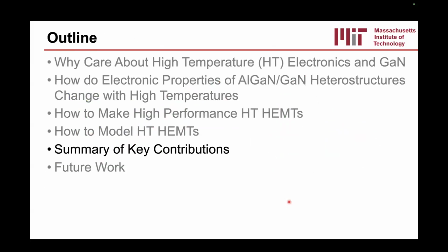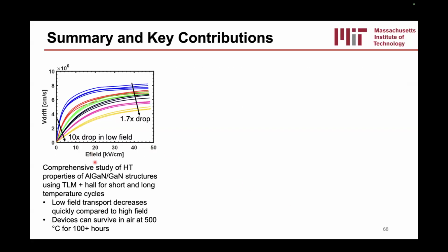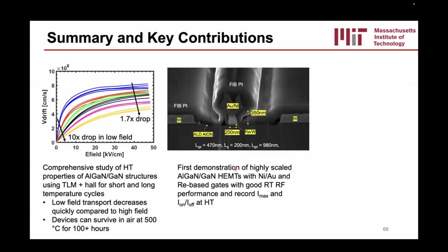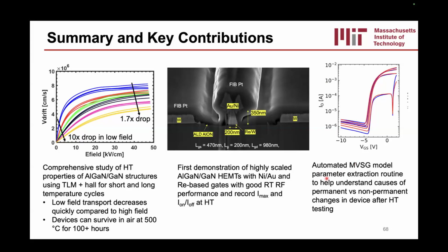Great. So I'll end now with a summary of some of the key contributions of this thesis. All right, so we've learned a good amount about the high temperature properties of GaN HEMT structures. Main takeaways here are low field transport decreases rapidly with temperature, but the high field transport really doesn't. And devices can survive in air at least for a few hundred hours, 100 hours or so, at least without any bias applied. We can also make demonstrations of really scaled nickel gold and rhenium-based gates with really good RF performance at room temperature and record Imax and on-off ratios at high temperatures. And similarly, we can make an automated modeling parameter extraction routine, which helps us understand permanent versus non-permanent degradation of the device as a function of temperature across various ramps.